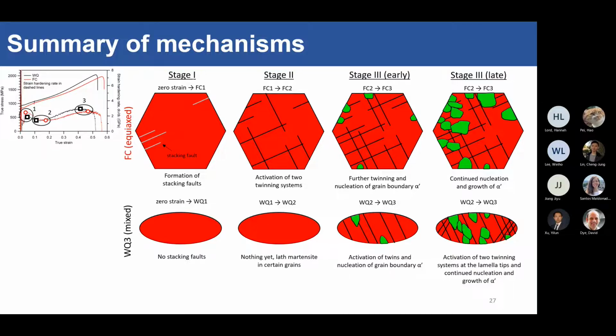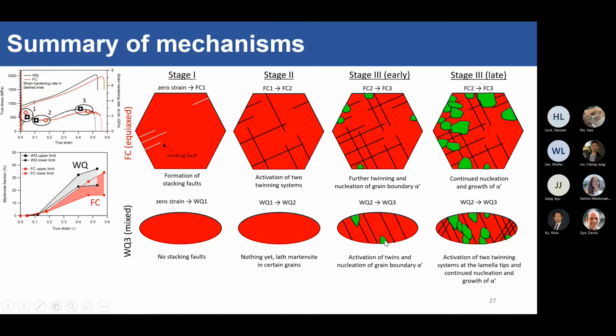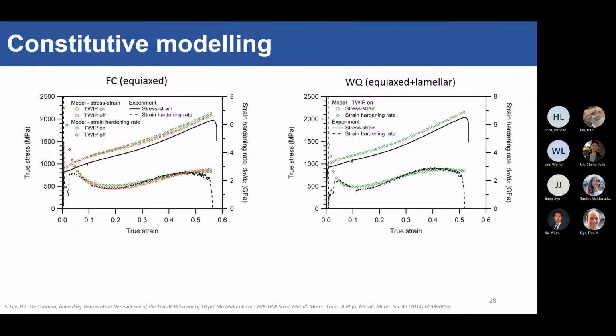So in the water quench sample, you have a much higher grain boundary area to volume ratio, and therefore you expect to have more martensite in the water quench sample. So we measured the martensite fraction by EBSD again, and it's true, we do form more martensite in the water quench sample, which is great. So now we took all the stuff that we've learned and we tried to feed it into a constitutive model. This model was developed by Lee and de Cooman, who really pioneered this medium manganese field. And you can see we've got fairly good agreement with the stress strain curve.